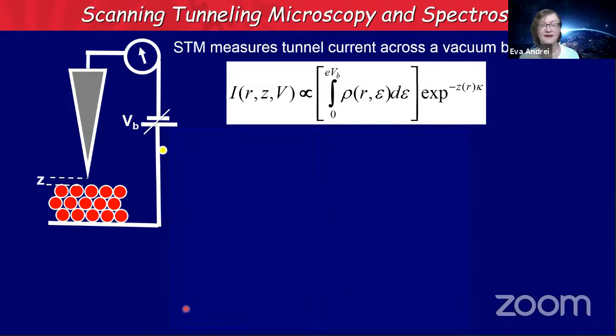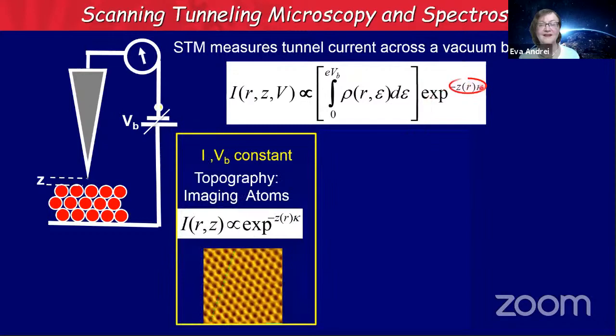And this is done with scanning tunneling microscopy. You bring a sharp tip to your metal, you apply a bias voltage, and you measure the current. And when the tip is close enough, you get a tunneling current here, which depends on two parameters. One is it depends exponentially on the distance between the tip and your substrate. And by rastering the sample, forcing the current to be constant and keeping the bias constant, and having a feedback motor, you can actually create an image of the atoms that you have in your lattice.